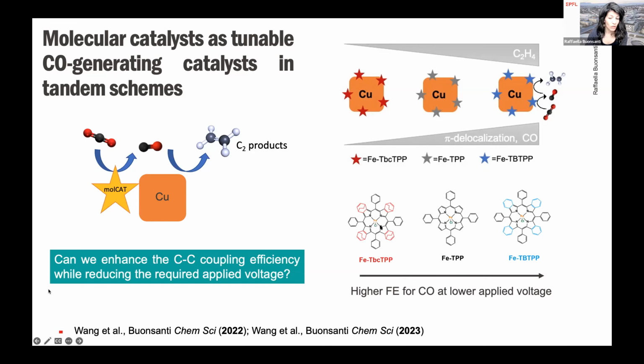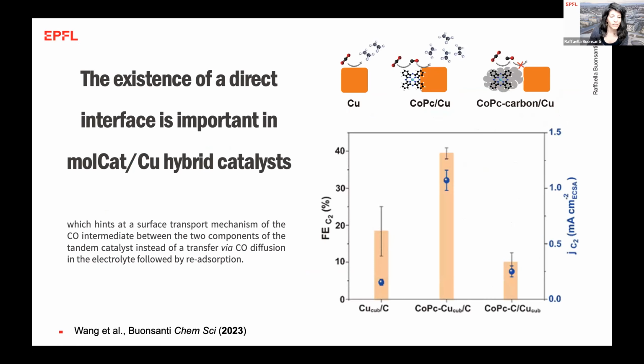And then because both the molecular catalyst and our nanocatalyst are soluble in solution, we can really start to mix them and to find the conditions, the loading, and the matching of the production of CO and the voltage that actually enhance the CC coupling also in this case. And what was interesting to discover here is that we actually need the molecular catalyst to be in contact with the copper in order to generate this CC coupling, and not simply in the vicinity of